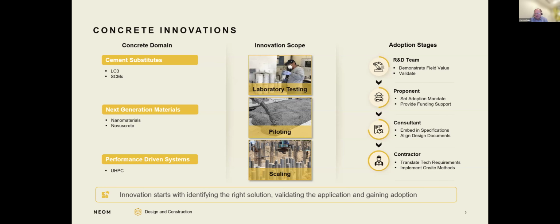So we've developed suites of mix designs from 40 MPa up to, when we get performance driven systems, 150 MPa. But our large mixes are in the 40 to 80 MPa range. And we have blends that go from 30% clinker substitution up to 65% clinker substitution with quaternary blends. And we are using those for some of our large foundations at this moment in time. So for the Line, for instance, our approved blend is a quaternary blend that uses GGBFS, natural pozzolana, microsilica, and OPC, with a 65% replacement of OPC. So very high substitution rates, and lots of tests for heat management as well.